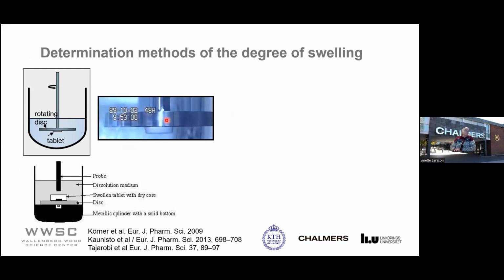So here is the metal that you glue a tablet on and place it in a release bath. Have it there for some time and rotate it. And then you unscrew the rotating disc, place it in a beaker, and you have a probe here. And this probe then can determine the force and the position. By doing that, one can determine where, when it hits the gel layer, the force increases. And when it hits the core, it increases even more. So therefore, you can determine both where the gel layer starts and where the core starts. So that is a very good method.